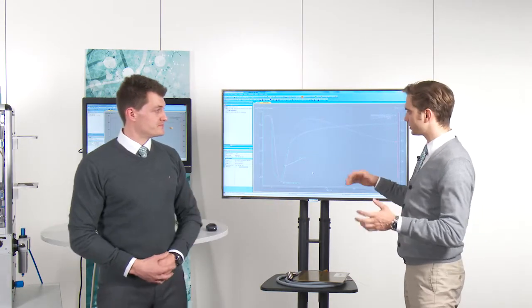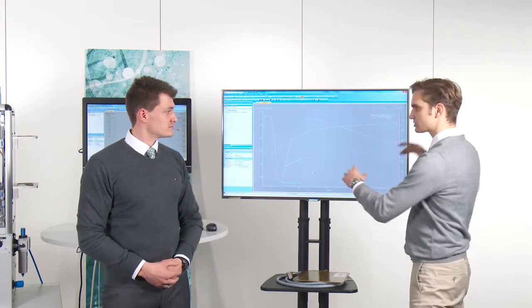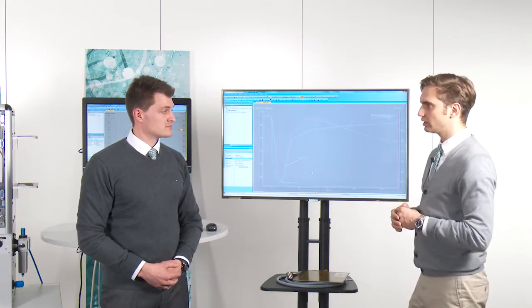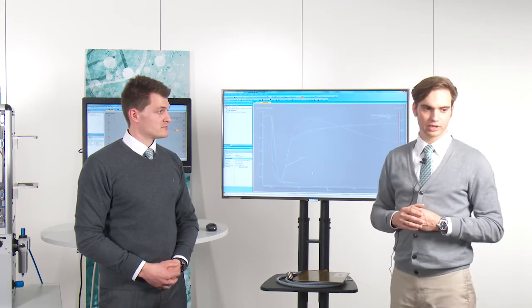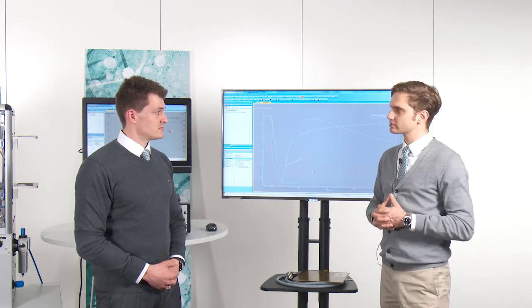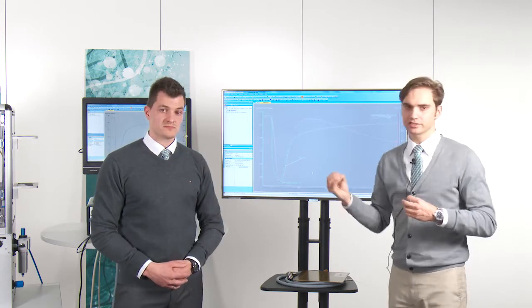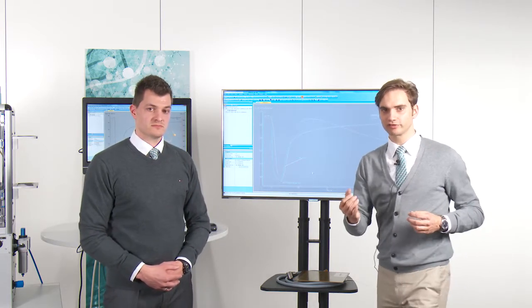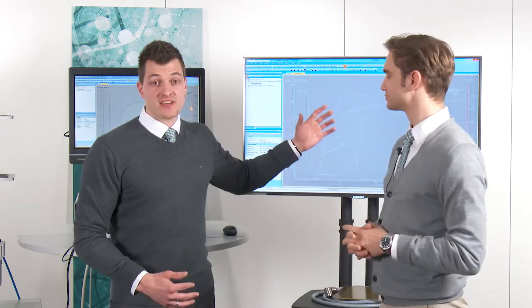Okay, so I can correlate the frequency response at different times to the state of cure. So I think we can answer the question with yes. I can use the DEA as it is the only technique that can stay with the process all the time. This kind of sensor gives you a possibility that no other technique actually offers. And especially, it's really hard to place a DSC inside the mold. So that's what you can do with the DEA. And like all thermophysical behavior, the dielectric also follows the time-temperature superposition principle.